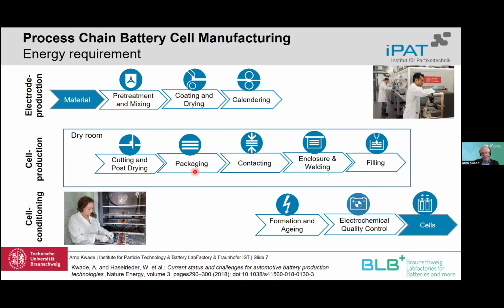We can contact all the different electrodes because there are more electrodes in a cell, which was also shown by Diego in the first figure. And then we have to close or package these electrodes into a case, which can be a hard case or it can be a pouch. And then we have to fill it with the electrolyte, which is very sensitive to moisture, as I said. And then at the end, we have to form the cell. So formation is something like starting up the cell, which is also very critical for the later performance, before we have the last quality control and we can sell the cells.